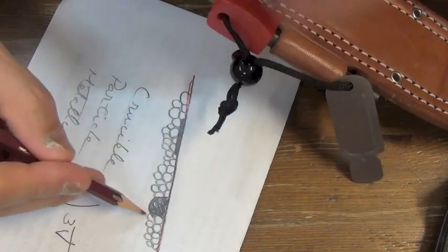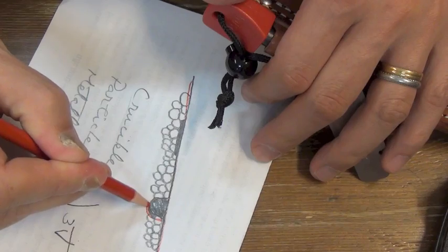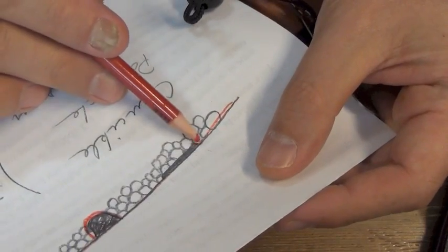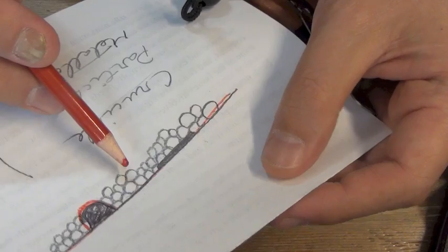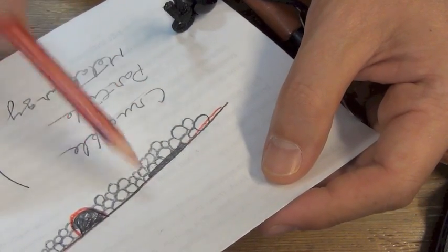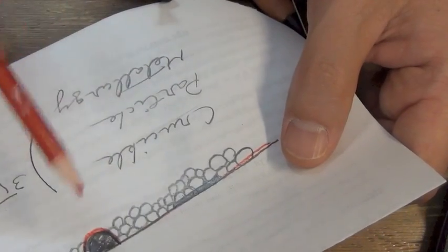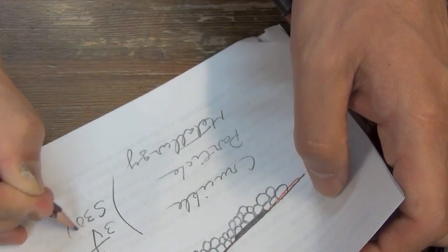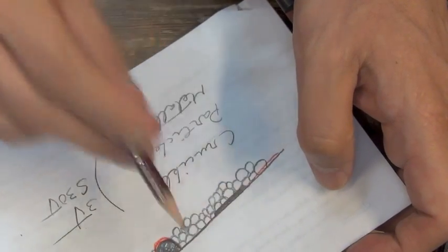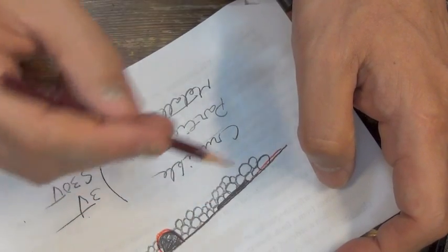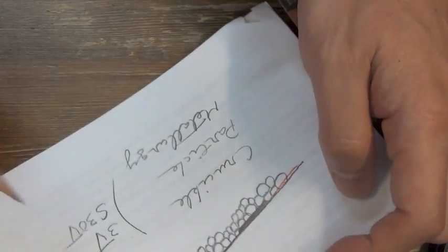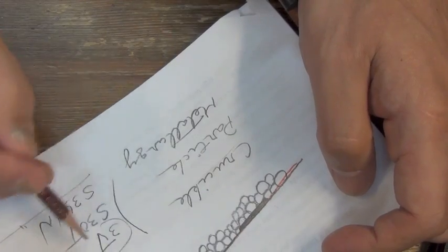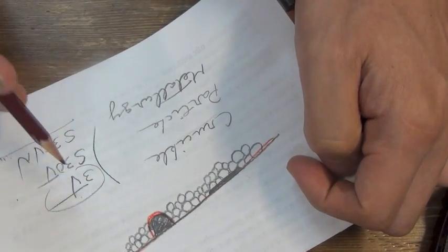This takes place because this bonding is weak in a small angle. This takes place because each particle is just hard but brittle. So this CPM 3V or S30V. And I experienced this phenomenon, this linear micro, not deep, micro snaps, to my S35VN a bit, a little. It is typically visible, happens on CPM 3V.